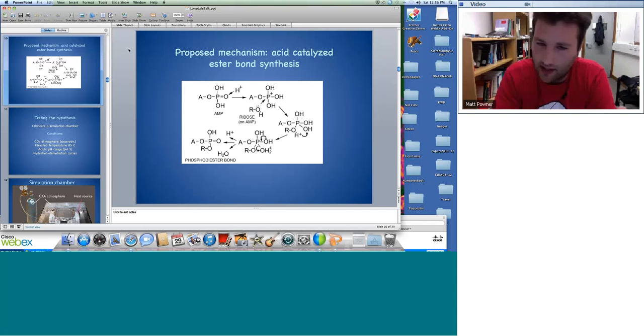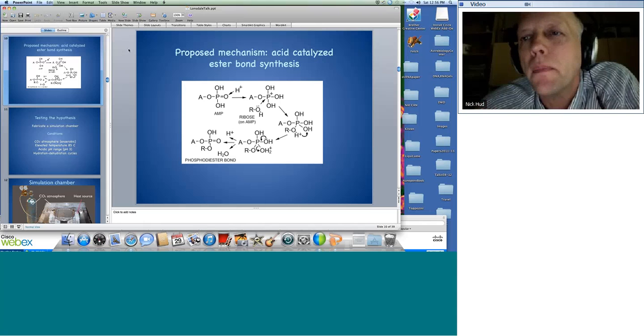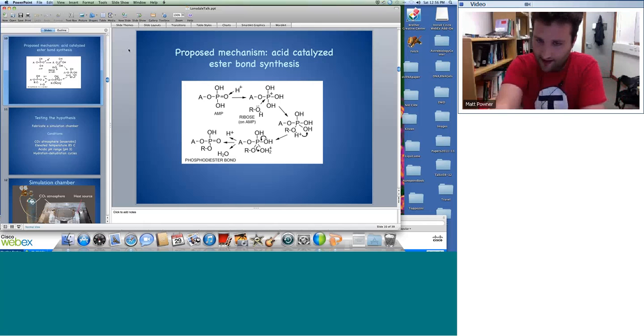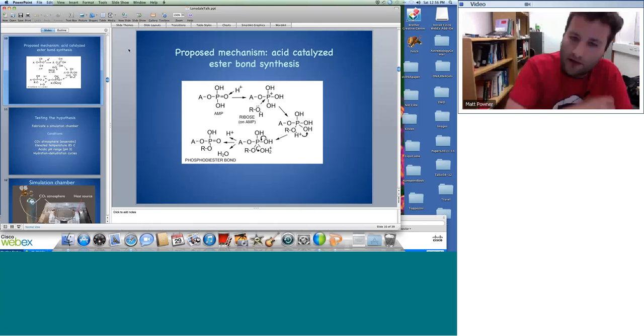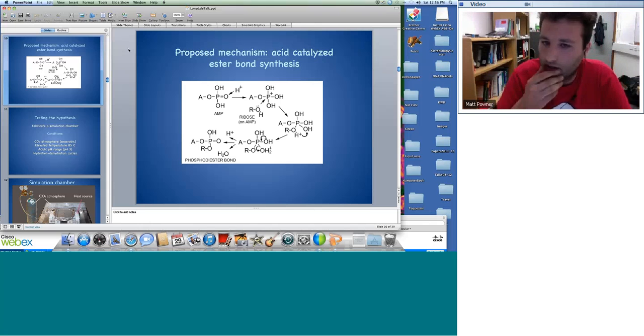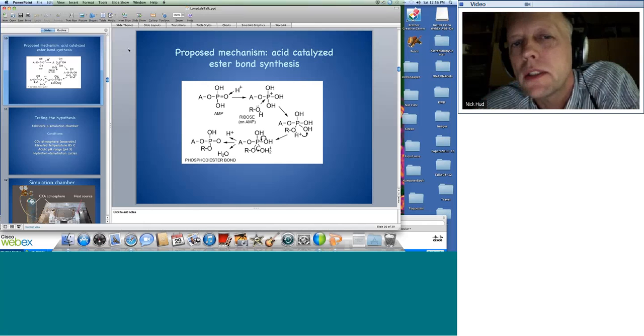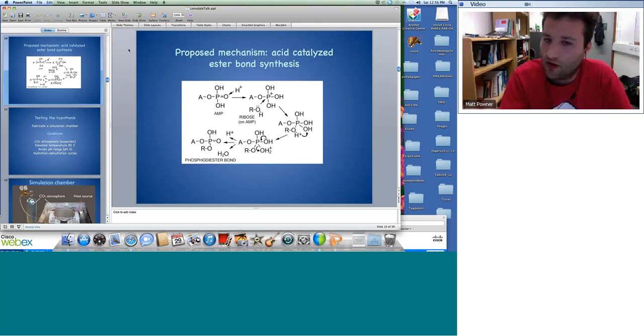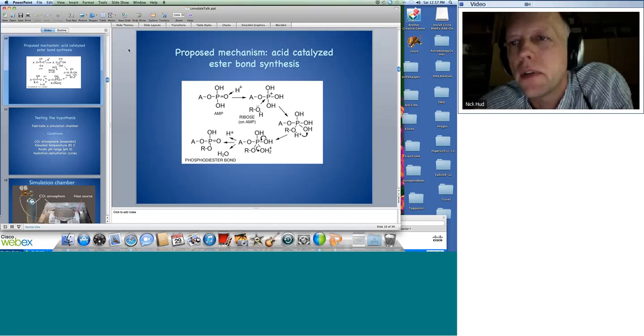If you get very low pHs, the pentavalent phosphoruses can shuffle. Okay, yeah. So in that way, your ammonia... I'm not suggesting David's mechanism is entirely wrong. I'm just suggesting that the ammonia might be providing a specific acid catalyst at a particular point in the reaction, which might amplify what he sees with ammonia relative to sodium and potassium. Right. I think what you're saying is that the proton he had coming in could be the ammonium ion coming in right there. Yes, the ammonium ion coming in and then loss of ammonia can really drive that forwards, leaving the proton behind. I'm fine with that.